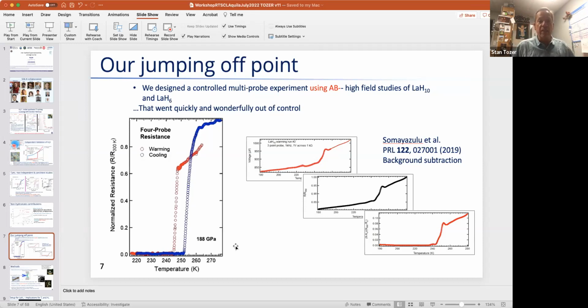But our colleagues discovered LaH10 along with Eremets' group, and I show the data here from that PRL paper of Somayazulu, or Zulu, or Z, depending on how well you know him. And again, you can see in the data set here that below TC there is a monotonically decreasing resistance, and it doesn't go to zero. But they had data on pure lanthanum, and because of that, they were able to subtract out or normalize the resistance and then subtract that out because they had data that clearly showed that this was a contribution from lanthanum.